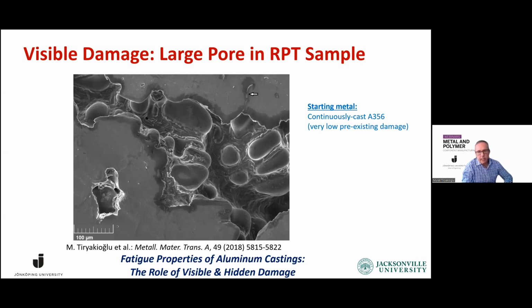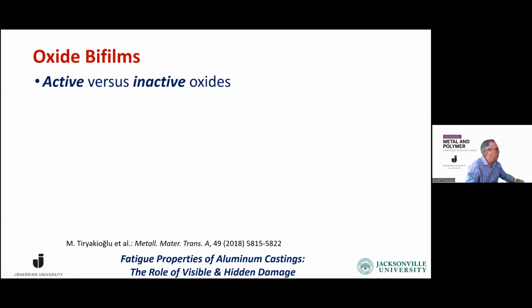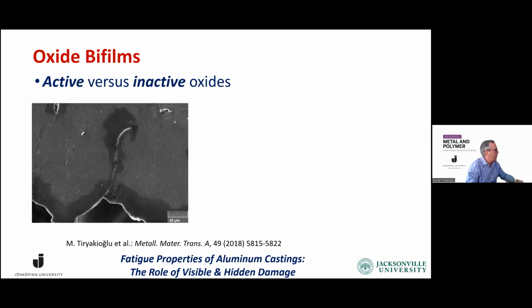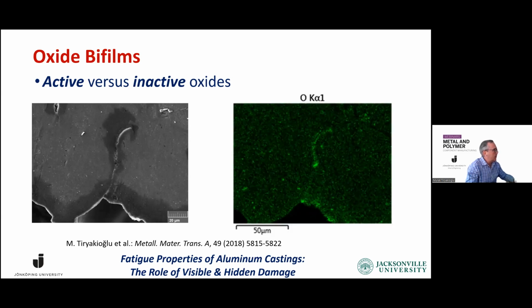And when we were looking at it under the microscope, we noticed this curious feature that you see with the arrow. And what is that? So we zoomed in, and looked a little bit closer. And when we turned on the X-ray map, it clearly presented itself as an oxide. So there was a folded bifilm, folded oxide, hiding there.